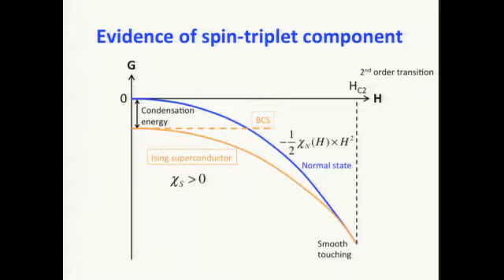So now the free energy gets modified into this form. I remind you again, this blue line is the normal state. The dashed line is the BCS superconductor. Now for the Ising superconductor, because of the spin triplet component, it has a finite spin susceptibility, so it also responds to the external magnetic field. You can see that they touch basically smoothly at a much higher magnetic field, so that it gives rise to a much enhanced Hc2 as well as the second order phase transition of the superconductor.